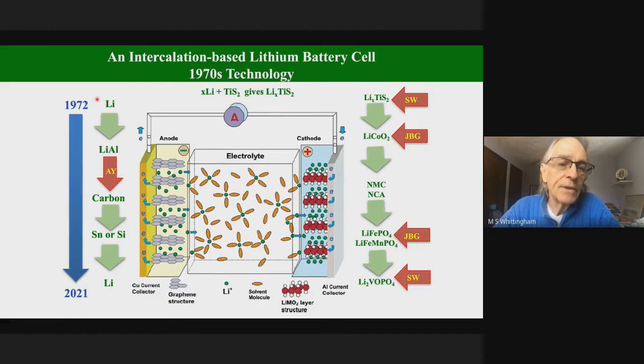So in 1972, we at Exxon used lithium metal. We learned that we form these dendrites. So we switched to using aluminum, and lithium reacts with aluminum at room temperature to form this one-to-one alloy. This works well for maybe 100 cycles, but it's not very long-lived. It was Akira Yoshino in Japan, who was working on carbon materials for batteries, who found out that graphitic carbon, as shown here, intercalates lithium very easily if you have the right electrolyte.